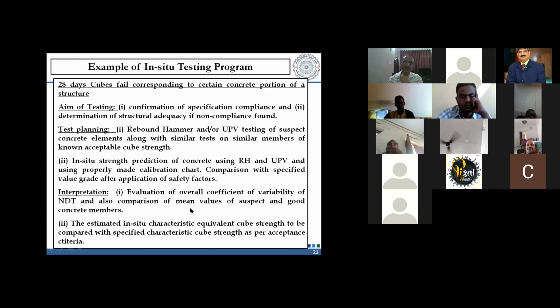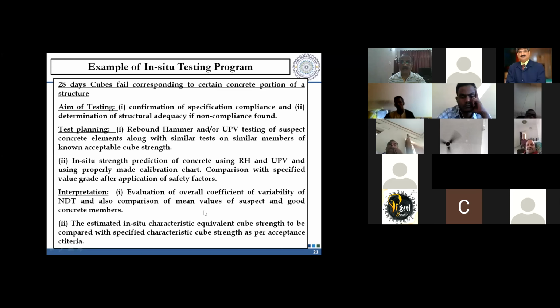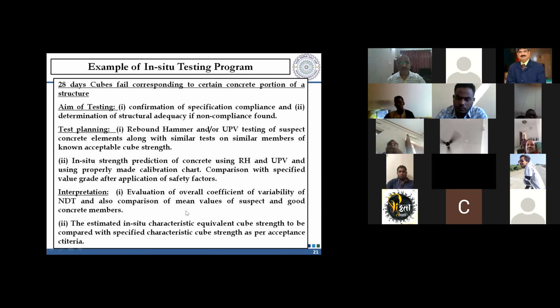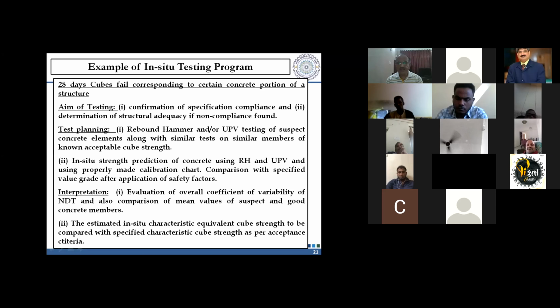If you get one peak, it means everything is fine, as far as variability is concerned. You're getting one peak, and if the coefficient of variation is also coming out within the range, it's all right. Even if you're getting two different peaks, one for the suspect case and another for the other case, but both the COVs appear to be all right, then also you can say that two different qualities have been used, but the mean value, standard deviation and coefficient of variation seem to be all right. If not, then of course that will come into suspicion.